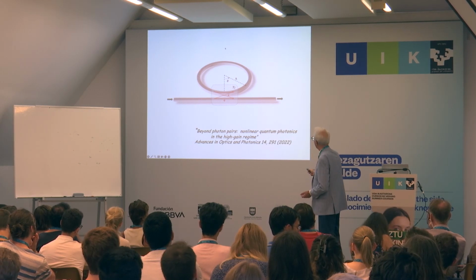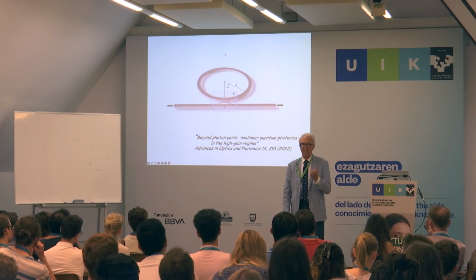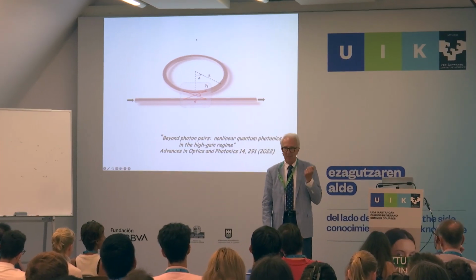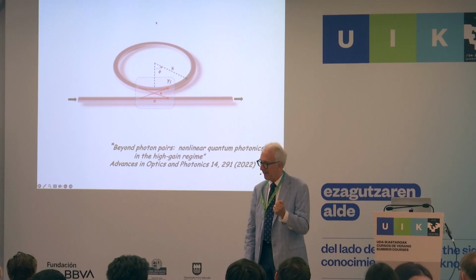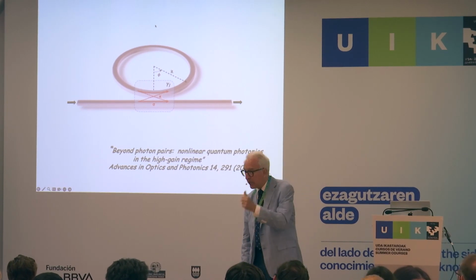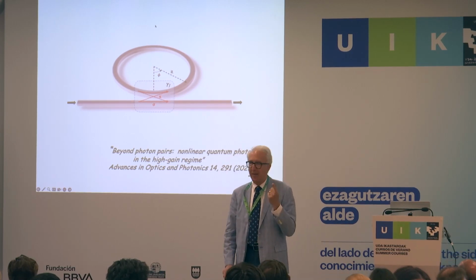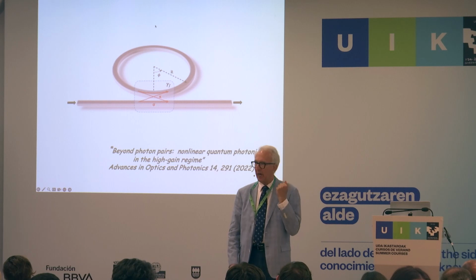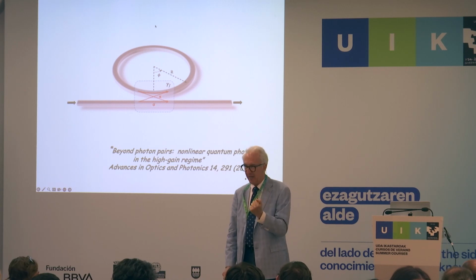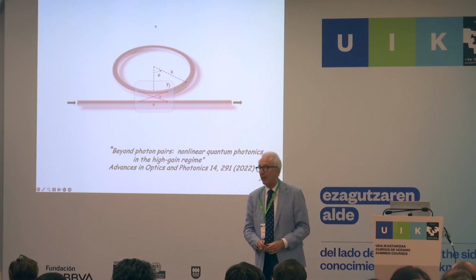The best material for this at the moment is silicon nitride. Okay? But if any of you have an idea for how to use some topological material to generate a large chi-3, okay, in a regime where there's no absorption: if you have entangled photons and you absorb one of them, the other one is of no use to you. Okay, so we want no absorption. We want a large chi-3. Okay, if you can come up with that, come talk to me and we'll write a patent together. Okay, I'm joking. But that would be an important contribution.